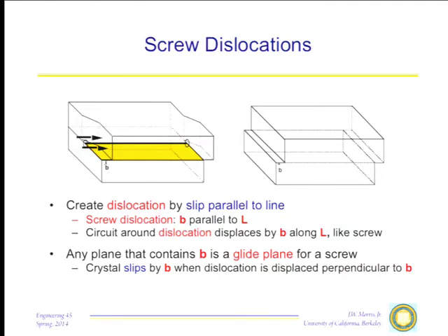There's another characteristic of screw dislocations. I mentioned an edge dislocation moves very easily in the plane, but it's difficult to move it out of that plane. That's not true of a screw dislocation. In a screw dislocation, the Burgers vector and the dislocation line are parallel. And this has the consequence that you can move a screw dislocation in any direction, and it will move conservatively and do what it's supposed to do. So an edge dislocation has a well-defined slip plane. Screw dislocation does not. The fact that you see well-defined slip planes in low-temperature deformation is telling you that the dislocations that are important almost always have at least an edge component, so that they have a well-defined slip plane.